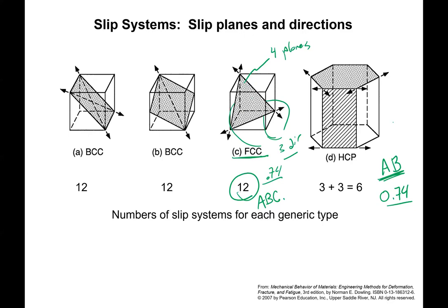Well, what that's also done is it's placed these high packing type planes all parallel to each other. So these basal planes, and that's it. The other orientations of this crystal don't have these 1-1-1, these are the 0-0-0-1 planes. So they don't have 4 like we would get in the face-centered cubic by cutting off each of these corners. And so our choices become very limited in this system in terms of the slip systems. And so in this case, we end up with only 6 versus 12, plus their spatial orientation is very limited.